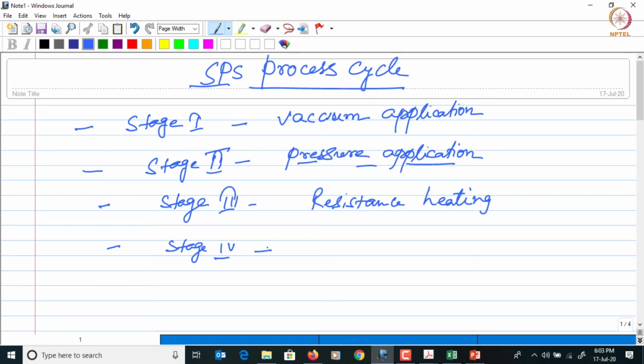This is also important because how fast or how slow the compact is cooled, depending on that, the microstructure can change. So SPS is a process which is quite often used for preserving a particular type of microstructure because of the rapid sintering which occurs here and the short sintering times. A particular type of microstructure can be easily preserved, which may not be possible in conventional sintering processes as the sintering cycle is quite long. So therefore the cooling rate or the cooling stage is also important in this case. And stage 4 is all about that.